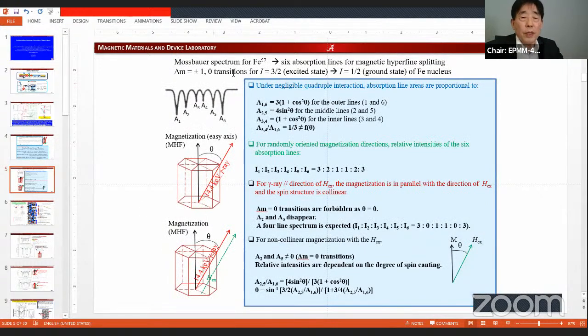Here are more details. So we have A1, A2, A3, A4, A5, A6. This is the area 1 of the first peak, area 2, second peak, and so on and so forth. And then this area ratio normally can be calculated by that formula right here. A1 and A6 are identical in area, A2 and A5 remain the same, A3 and A4 remain the same, depending on the angle right here. The gamma ray direction makes an angle against the c-axis of this hexagonal structure right here.